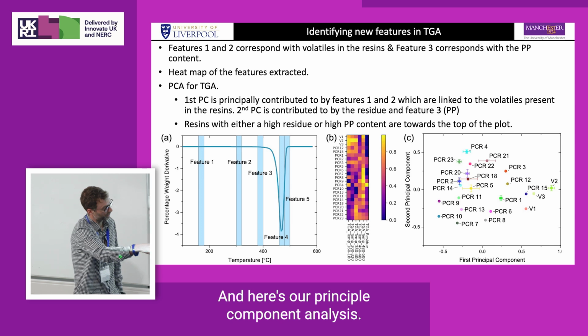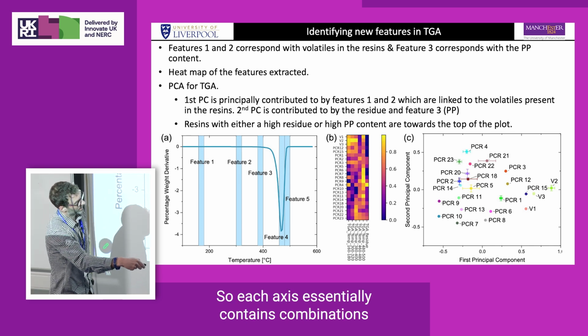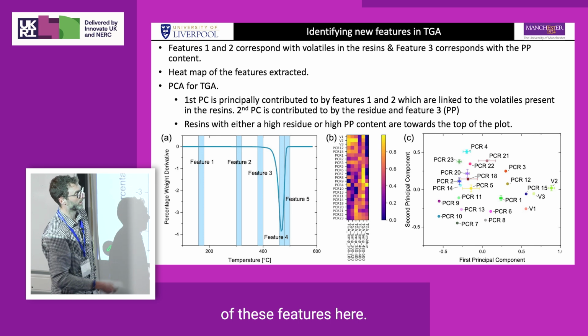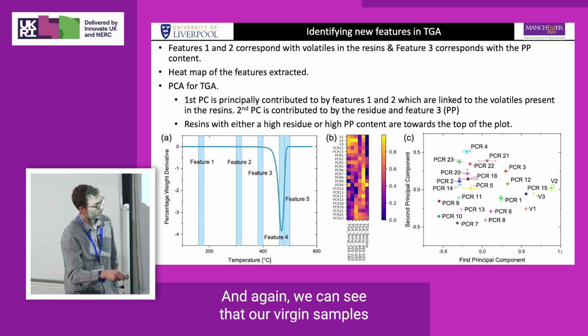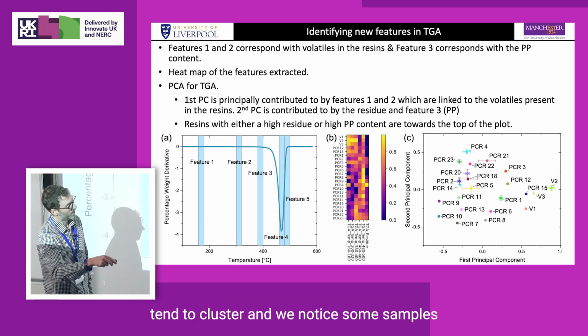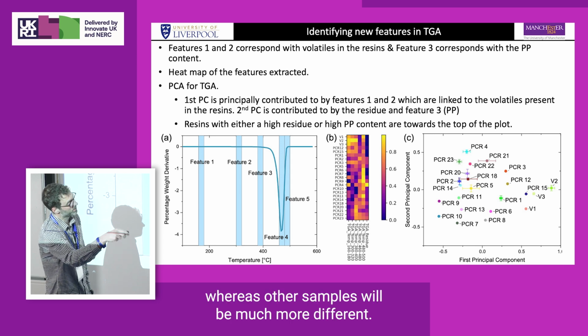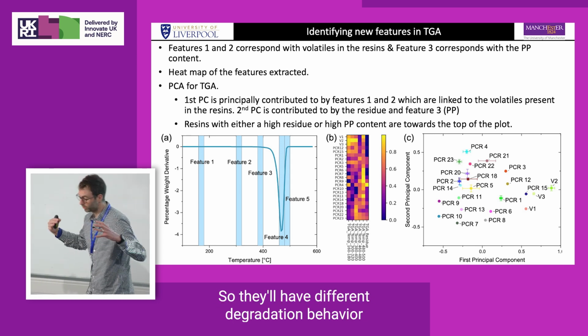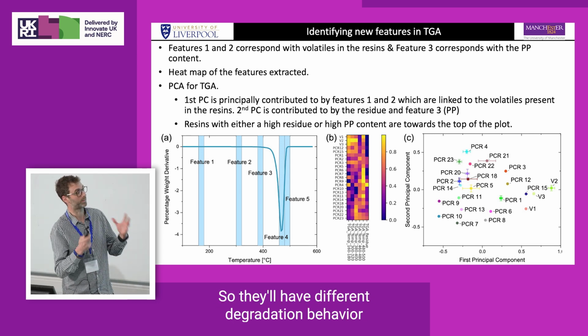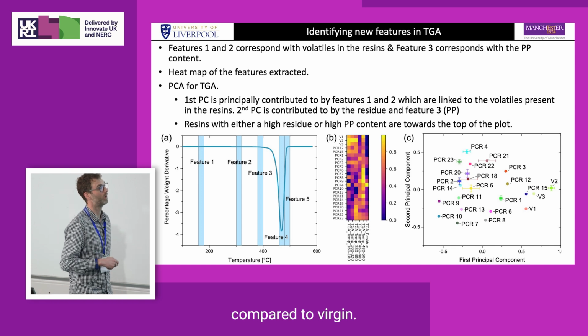And here's our principal component analysis. So each axis essentially contains combinations of these features here. And again, we can see that our virgin samples tend to cluster, and we notice some samples are closer than those, whereas other samples will be much more different, so they'll have different degradation behavior compared to virgin.